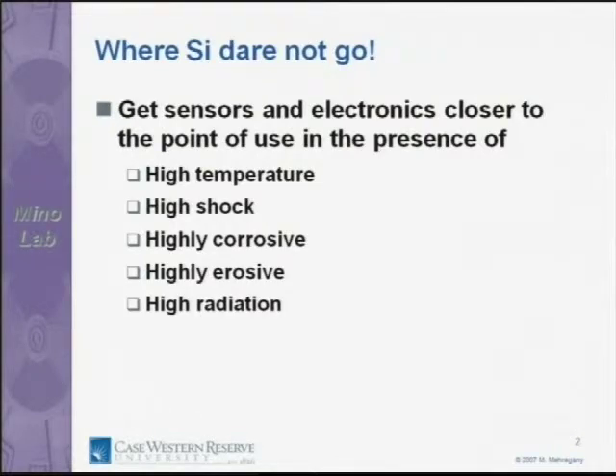So my interest in silicon carbide arises from the fact that there are many applications where silicon cannot go. These applications are typically known as harsh environment, but most notably high temperature and high radiation, highly corrosive, erosive environments. And when we say high shock, this is extremely high shock on the order of 60,000 G and higher. And some of the missile systems actually require that sort of measurement in the presence of that level of shock, some of them going up to 200,000 G.